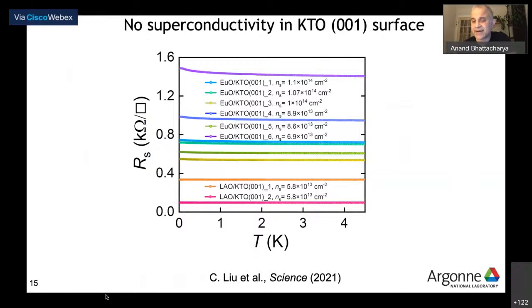And what was really intriguing right away was that for the same set of densities, if you look at the 001 surface of KTO, which is a much better studied, very widely studied surface, you have essentially no superconductivity as far as we could see. So that's a puzzle. That's the first big puzzle. Why is that the case? Maybe there's something special about the 111 surface.